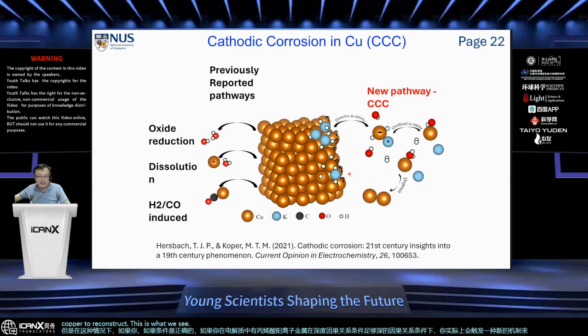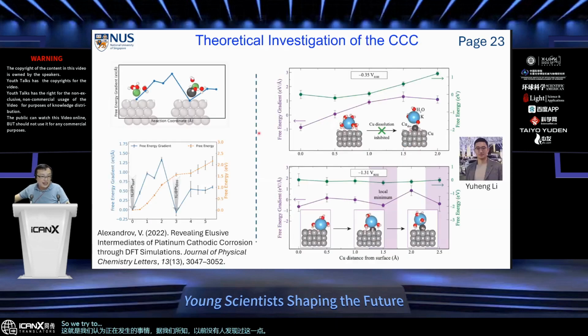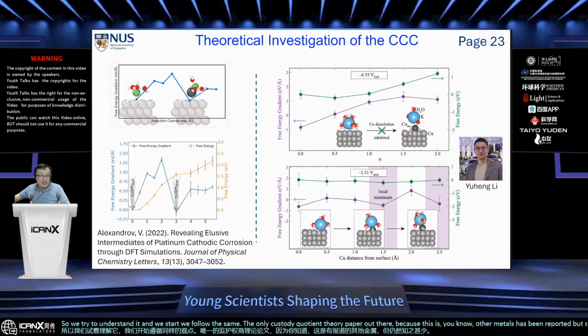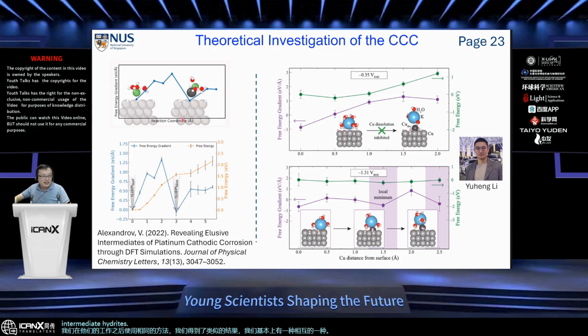And this is what we think is happening, and no one has found this before, to the best of our knowledge. So we try to understand it, and we follow the only cathodic corrosion theory paper out there, because this has been reported on other metals but is still poorly understood. We use the same method following their work, and we got a similar result. Basically there is an intermediate hydride species that is very unstable. You cause the metal to leave the surface, but it immediately gets oxidized and then deposits back. This is exactly what we observed in the TEM, the morphology change and the deposition of small particles.